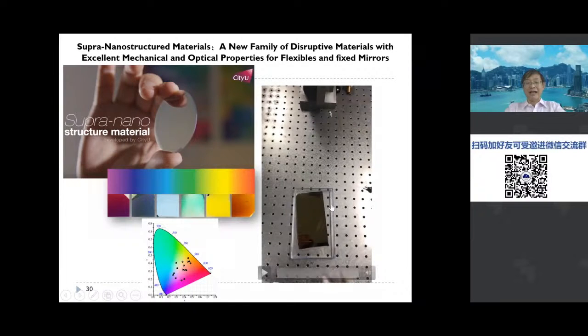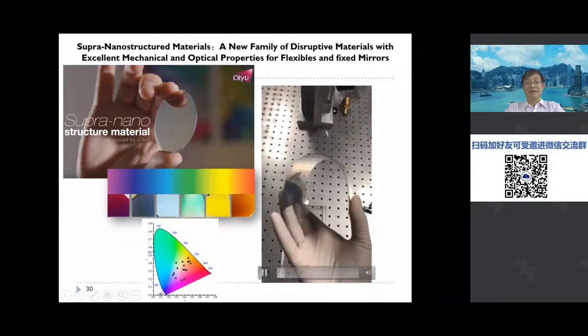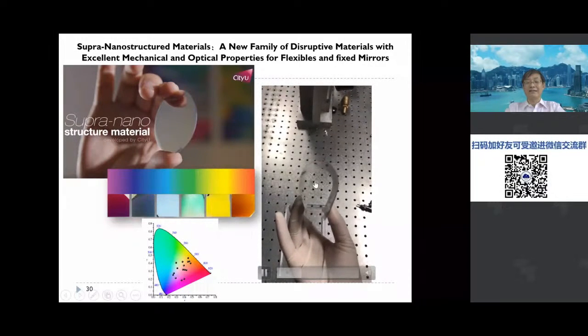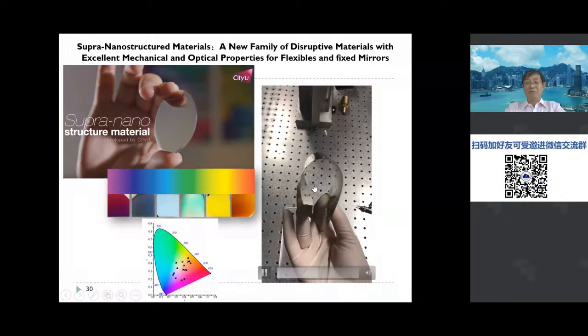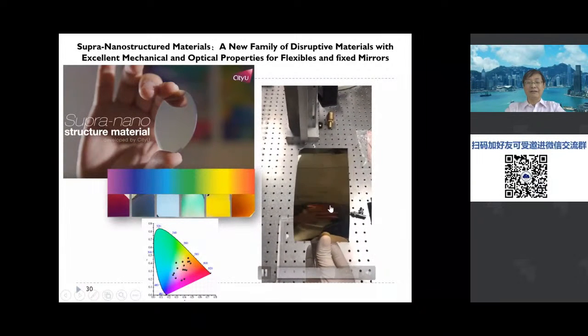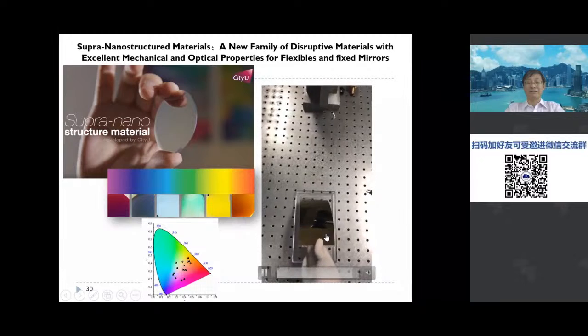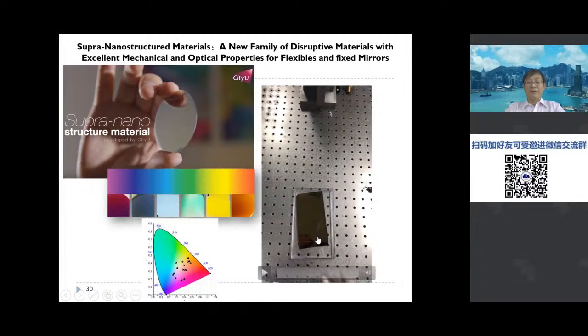dual phase. And then according to the needs, we can obtain different optical properties using this dual phase with a very strong mechanical property. Quite often we have a polymer material that needs enhancement of mechanical property, and also needs a reflective material on the polymer's weak spots. So it's a combination of structure and functional property on the polymer. This technology can easily apply to all polymer materials to give this mechanical enhancement with different types of color.